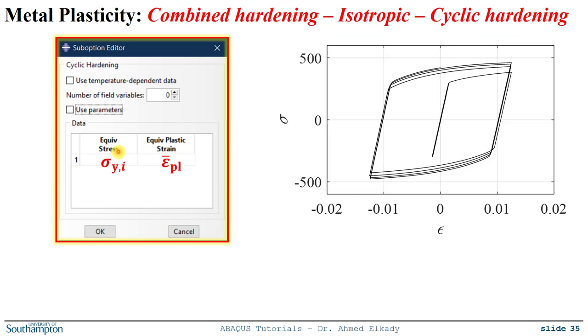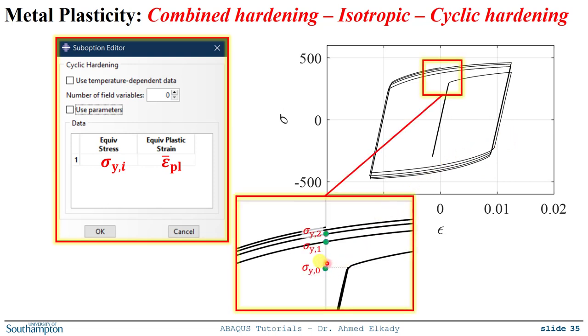So how can you obtain this data? Again, if you have a symmetric cyclic coupon uniaxial test with a constant amplitude, you can take this data and get this data point. Since this is isotropic hardening, you want to capture the change in the size of the yield surface with accumulated plastic deformations. So you can get the value of the equivalent stress at each cycle. Then, in MATLAB or Excel, you can compute the equivalent plastic strain, which is pretty much the accumulated integration of the logarithmic strain of your coupon test. FYI, the equivalent plastic strain goes from zero upward, so it's always increasing.